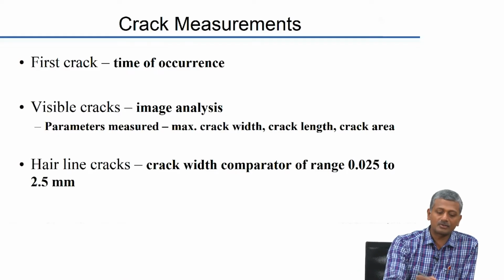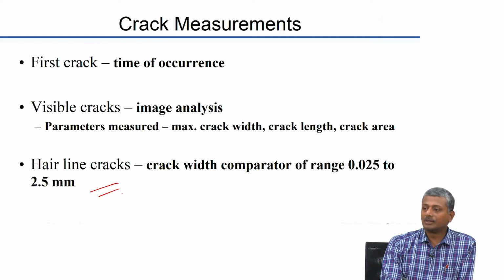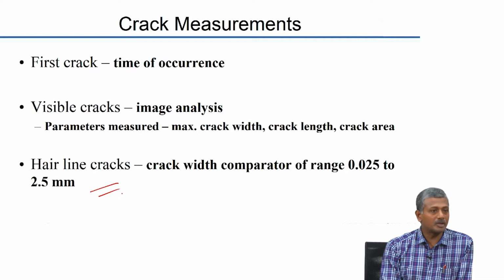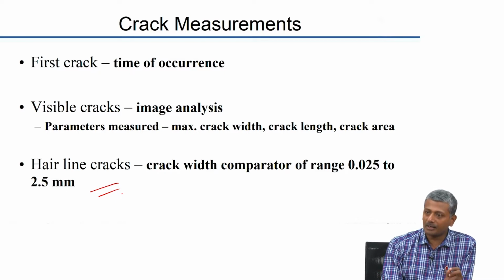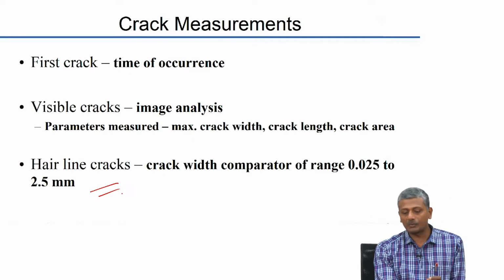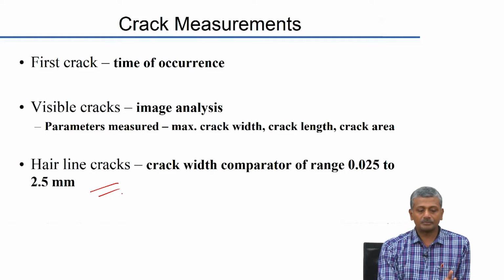So, the size of the cracks, so that we can correspond the crack size to be either a hairline crack or a large crack. There were visible cracks which could be directly obtained from the image analysis itself, but for very small hairline cracks, we had to actually do the crack width comparator measurements. The other thing which we noted was the first crack occurrence time.